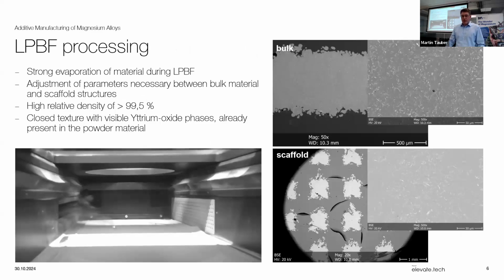The next slide shows the LPBF process itself. It's quite familiar to many of you probably, but it's not too familiar for the manufacturing of magnesium, because magnesium has some specialties with it. It's really, really light. So if you have a gas suction, you have to find a really narrow spot where you have enough gas suction to get rid of the vapor that you see here, but you don't want to suck away all the powder from the powder bed. So this is a really small sector that you have to work in.